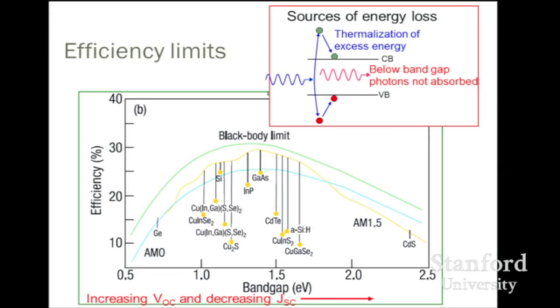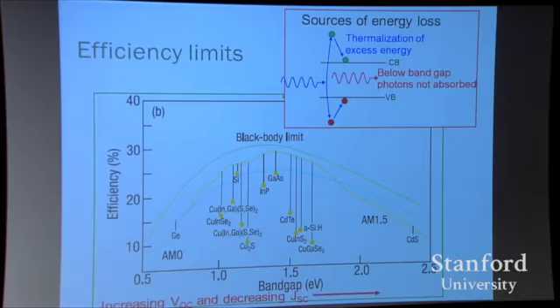And as many of you probably know, the fundamental problem we run into when we try to go over 30% efficiency is that when we excite carriers up into the gap, up into the conduction band, they rapidly relax to the bottom of the band and we lose that energy. And that makes us want to use a high band gap to avoid the thermalization losses. And if we do that, we can get a high voltage, but then we can't absorb the low energy photons.